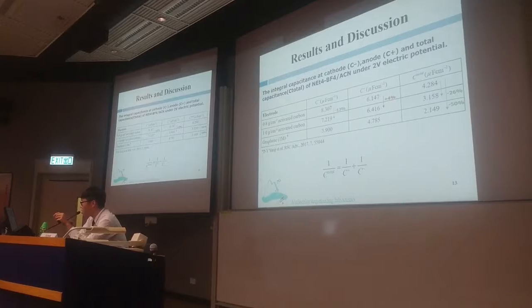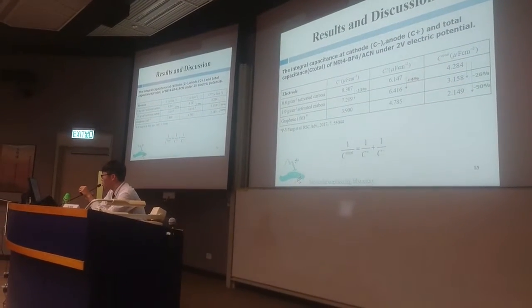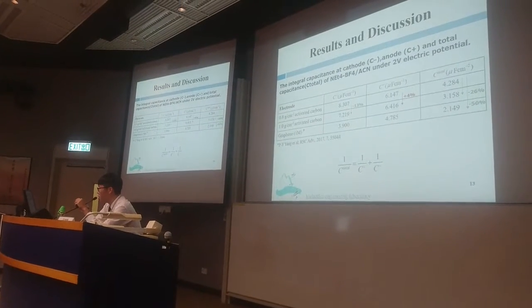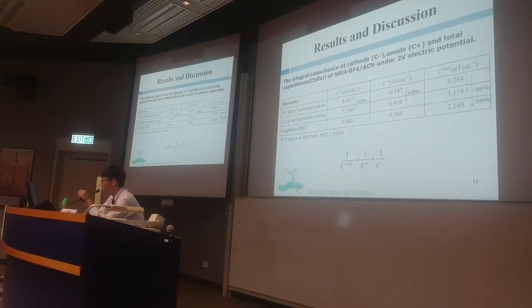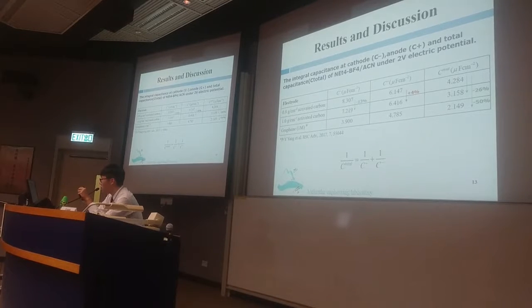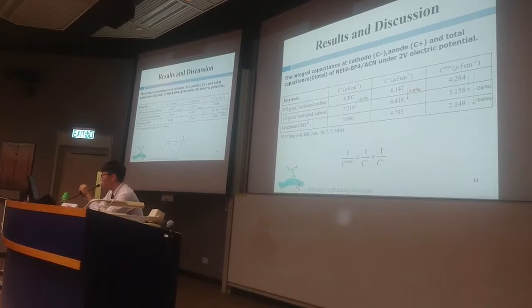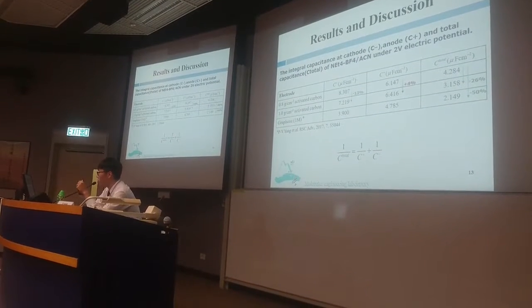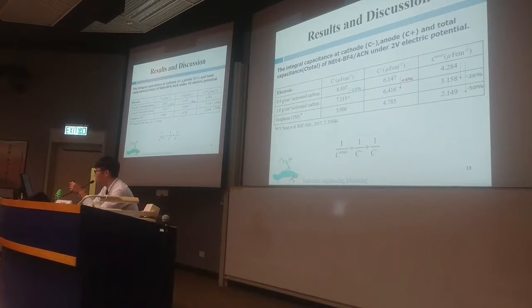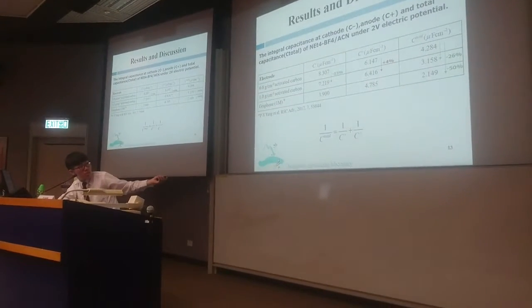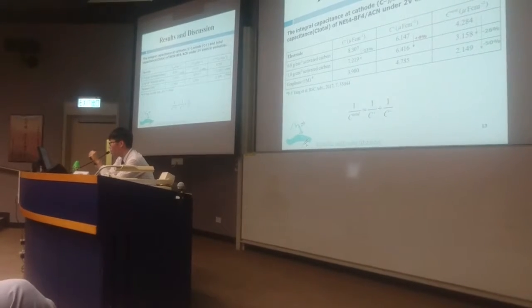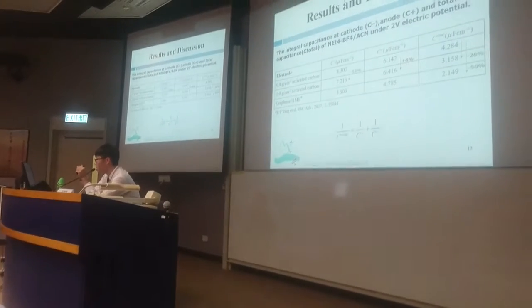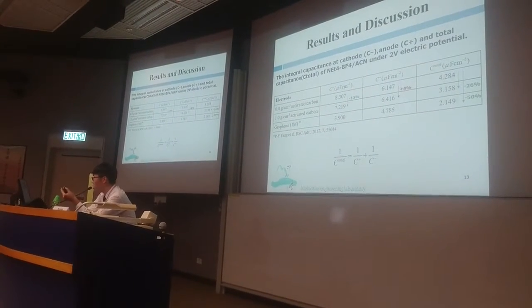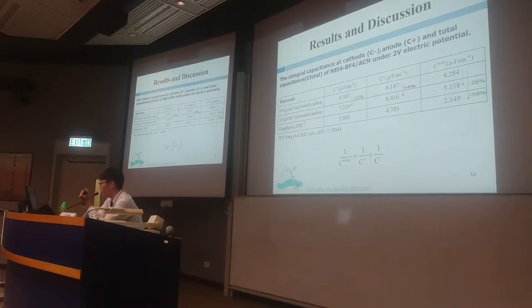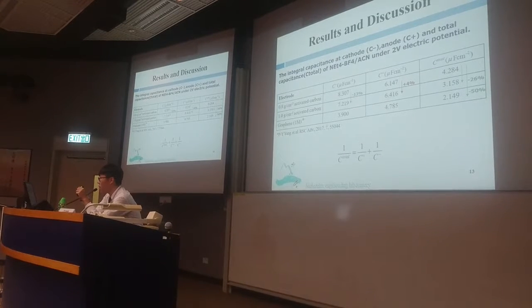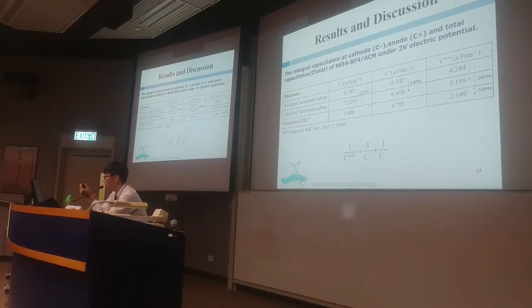Finally, the capacitances are listed in this table, for the different densities of AC carbon electrodes and the graphene electrodes published in our previous work. The total capacitance is calculated from the corresponding integral capacitance at cathode and anode under the 2 V electric potential by this equation. Comparing the capacitance of the AC electrodes, the lower density 0.8 AC electrode has higher capacitance. That's because the lower density AC electrodes give more space for ion adsorption.